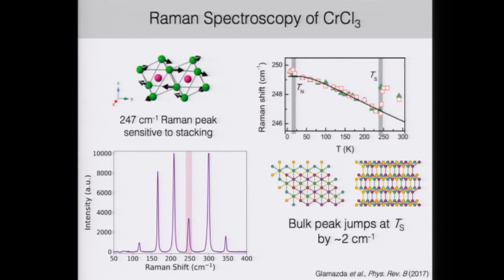So one way to analyze the stacking symmetry is to turn to Raman spectroscopy. So we looked through the literature and identified that in bulk chrome chloride, it's been seen that there's this mode in the Raman spectrum at 247 wave numbers that undergoes a shift in energy by about 2 wave numbers at 240 Kelvin right at the stacking transition, where it goes from the monoclinic phase at high temperatures to the rhombohedral phase at low temperatures. And then we took the spectrum ourselves and saw that this is quite a nice peak that we can easily study in the bulk and thin limits.